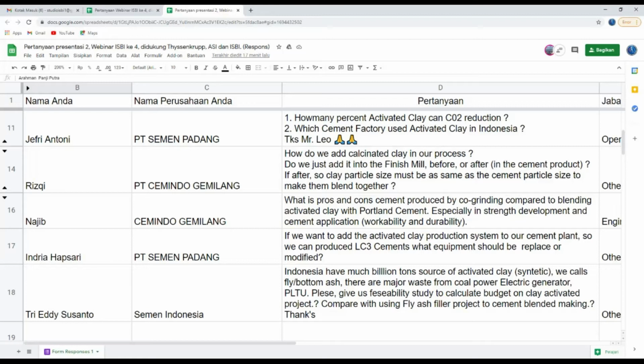This is depending on the cost for fly ash and also depending on the needed quality. So we think that we can substitute more clinker when using activated clay than using fly ash because the activated clay has a higher activity. So in this case, we have to compare which amount of clinker can be saved when going to activated clay. And we have to put in the cost for the fly ash today, as well as the production cost for the activated clay. And with this, we can build up a feasibility study. This is no problem, just contact Ridwan. And we can also then share some costs here.